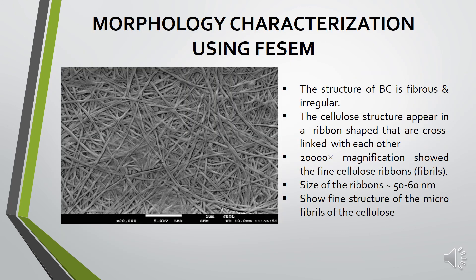For the morphology characterization using FESEM, it can be observed that the BC is made of ultrafine layers of cellulose ribbons that are crossed, superimposed, and randomly oriented — also called microfibrous — irregular in size, where the size varies from 50 nanometers to 60 nanometers. There is no presence of cell biomass embedded in the BC matrix, as the sodium hydroxide solution is able to hydrolyze and remove all cell impurities even at low temperature.